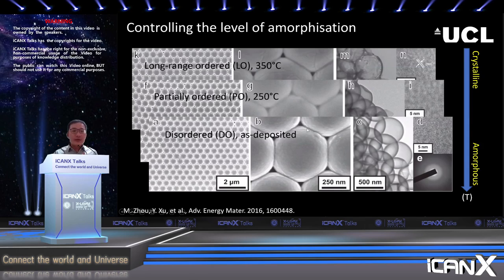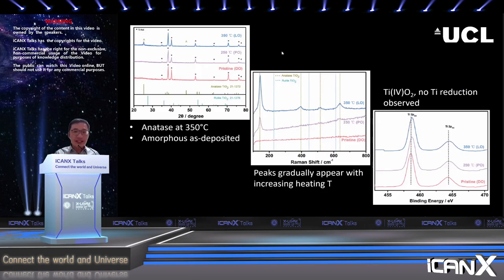And we can also see from this characterization that the geometry, the size, the thickness, everything else is identical among the 3 samples. We also use a combination of XRD, Raman, and XPS to verify if the materials are as what we think. By increasing the annealing temperature, we can increase the crystallinity. So by lowering the temperature, we maintain the amorphization of the material.